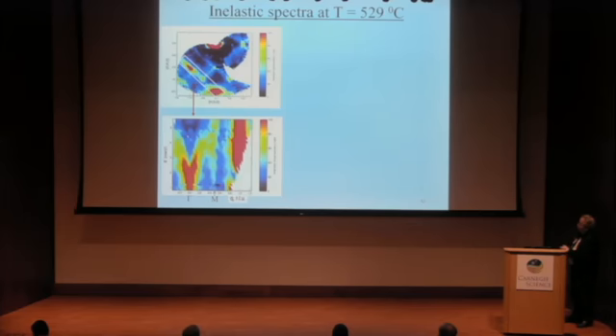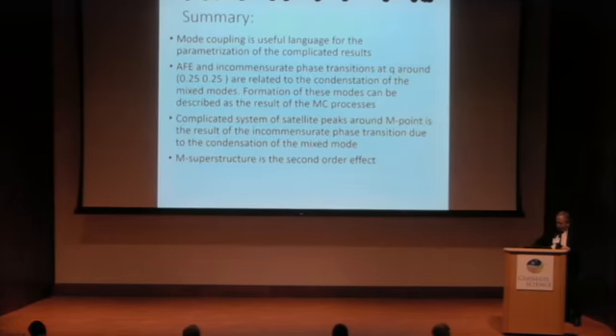And if we look now at the dispersion, we perfectly see the dispersion curve for the acoustic mode going up. So there is some rising of quasi-elastic scattering here, and nothing on the other side. So that's a situation very similar to what I have described. So I will skip this.